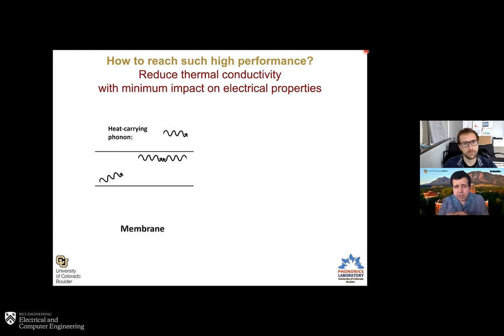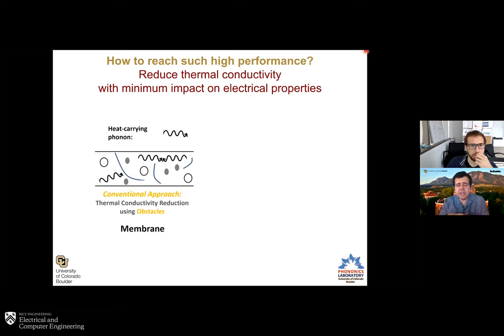I'm going to use a few cartoon-type schematics just to demonstrate some of the basic high-level ideas. So consider a cross-section of a membrane, and use this symbol to describe phonons. Phonons are traveling, carrying heat, and scattering. As I said earlier, the conventional approach is to introduce obstacles: interfaces, holes, inclusions, and so on. But ultimately, that will impede the electrons as well. Of course, you can try to optimize, considering the mean free path of electrons versus phonons, and somehow find a sweet spot. But still, it's really a very tight trade-off to navigate around.